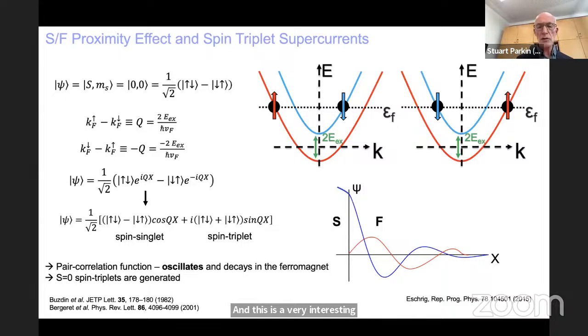And the basic idea is that if you take a conventional superconductor shown as S, and you form an interface with a ferromagnetic material, then typically the exchange field in the ferromagnet will quench the superconductivity because the superconducting Cooper pairs want to have their spins antiparallel. However, there's a possibility of forming in the ferromagnet no longer conventional Cooper pairs, which are spin singlet, but spin triplet pairs. And the reason for this, if you look at the energy band diagram in a cartoon fashion, the energy versus momentum of the spin up, shown in red, and the spin down band, shown in blue, then they exchange split, as in all ferromagnets. And this means that at the Fermi energy, the spin down and spin up electrons will have distinct K vectors. So now when you form a Cooper pair, there will be a finite K component.